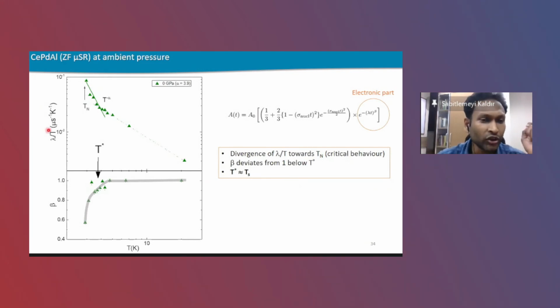Okay, so let us concentrate on the temperature dependence of lambda over T. As I told you, in principle, it should show some power law behavior towards the ordering temperature. And indeed, it is more or less showing some power law behavior for this cerium palladium aluminum at ambient pressure. Not only that, in order to deconvolute the spectra of the electronic part, we have seen that you need to employ a parameter called beta, which is well known as the stretched exponential parameter.